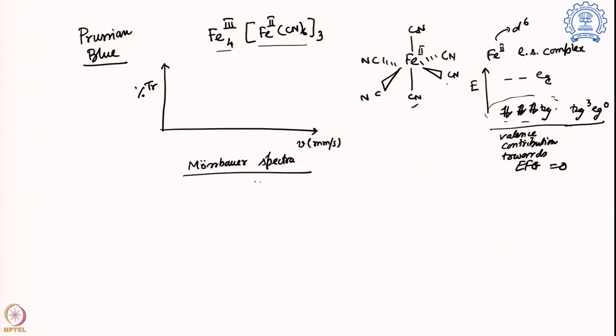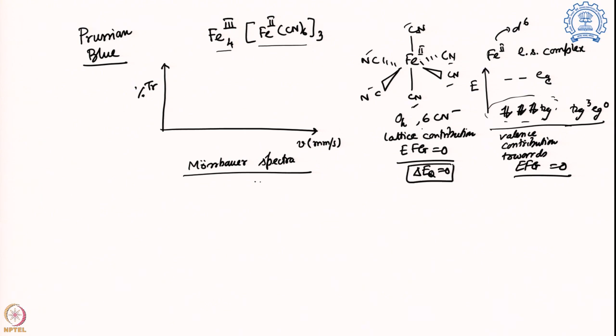And on the other hand, coordination-wise, do we expect a lattice contribution? No, because it is a perfect octahedral geometry with 6 cyanide ligands. So the lattice contribution for EFG is also 0. So this iron plus 2 sample has valence contribution 0, lattice contribution 0, so that means it is not going to have any delta EQ value, that is also going to be 0. So no splitting, we will see only one band representing the isomer shift of this iron plus 2.